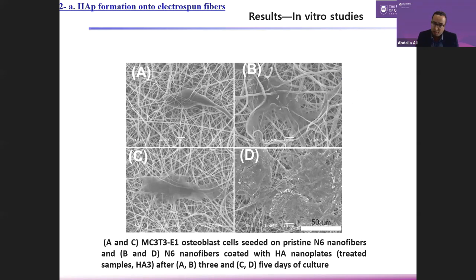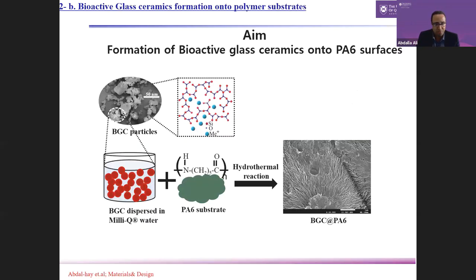In cell culture, it has osteoblast properties. We did gene expression, we also did conductive properties as well as ALP activity, and it showed definitely that hydroxyapatite on the surface enhances the biomineralization.